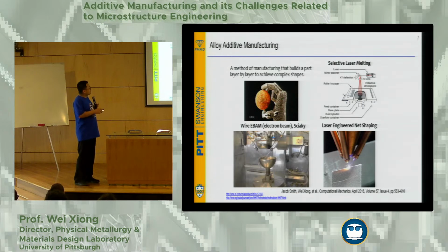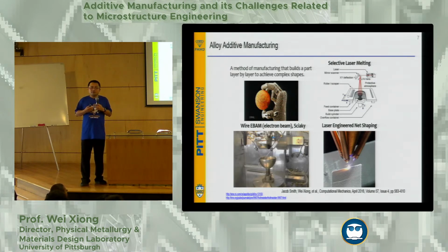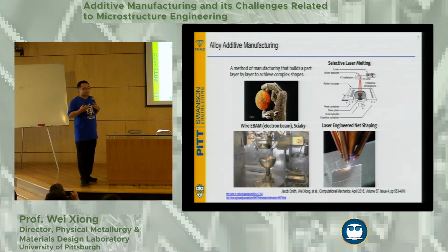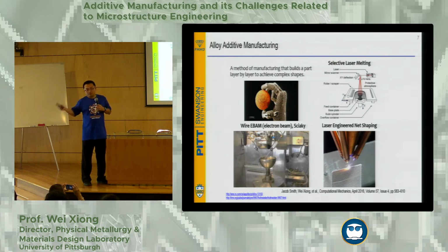So the advantage of the first process is certainly that you'll be able to print fine structures—the features of the microstructure are actually much finer than with wire or powder. However, the advantage of the other two is that you can print different alloys at the same time. Typically you can use two wires simultaneously and feed them into one material. You control the feeding rate, and therefore you can print so-called functionally gradient alloys or materials—printing alloy A to alloy B, and so on.